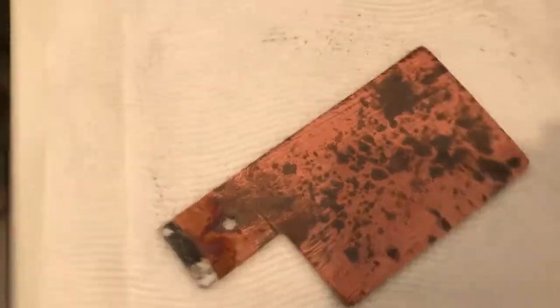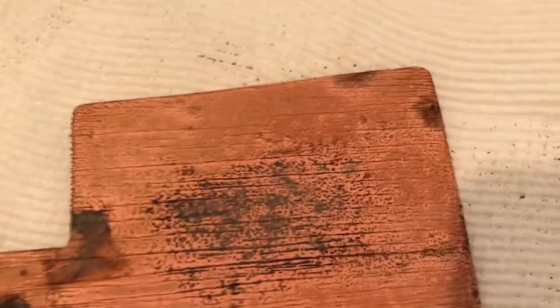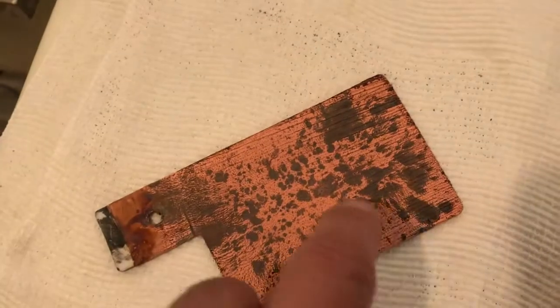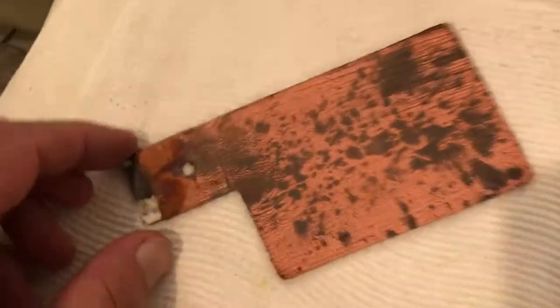I don't know what that is. It's a blemish on the surface, or is it in? The edges are completely done, so it's a self-contained shell. Copper coated plastic plate. It's oxidized, as you can see. I checked the spots from that point up here to anywhere on the surface, even on the dark spots, is 0.5 ohms on this one. Same with the other one.